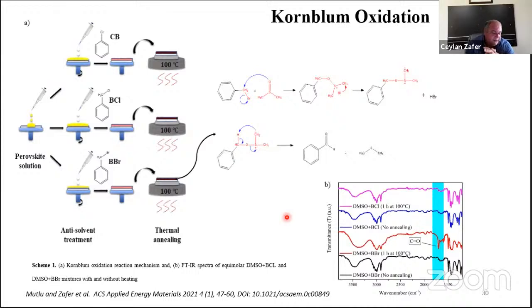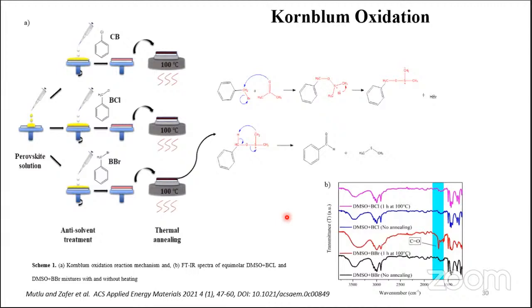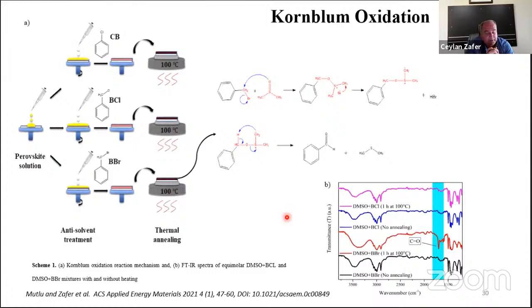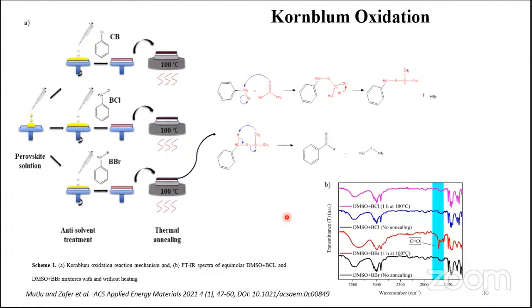And in the literature, it's very well known for perovskites that DMF and DMSO with the ratio 1:4 is the best configuration for the preparation of efficient solar cells. But the disadvantage of this mixture is that DMSO and DMF are very strong coordinating solvents, making coordination with metals like lead or tin. These coordination products, or let's say byproducts, act like traps or non-radiative recombination centers, which inhibit the charge transport within the device or within the perovskite structure.